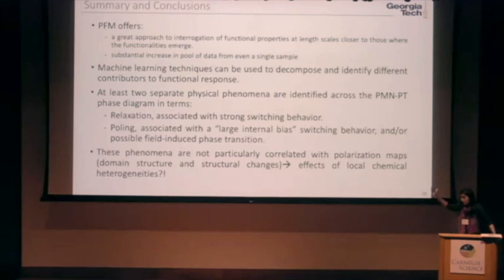So, first of all, we wanted to remove that issue, so that's why we worked with single crystals, 001 cut single crystals. And you're absolutely correct, it could be related to the domain structure, so what happens if I already have a polarization that is lying in plane and I'm pulling that one up? We could not find a direct correlation comparing with both the out-of-plane and the in-plane polarization. The phase of the piezo response that you observe is directly correlated with the out-of-plane and in-plane polarization components, and we could not find really a direct correlation.